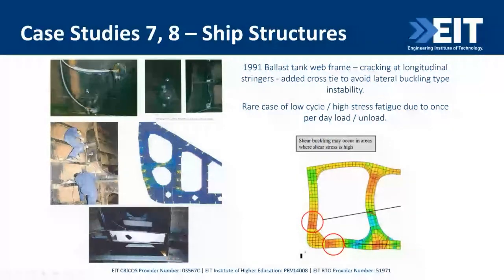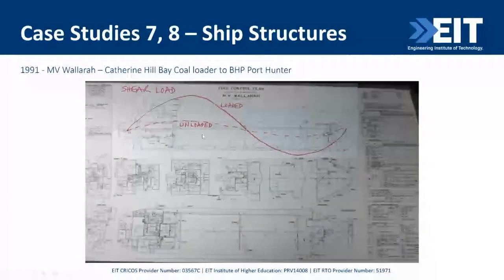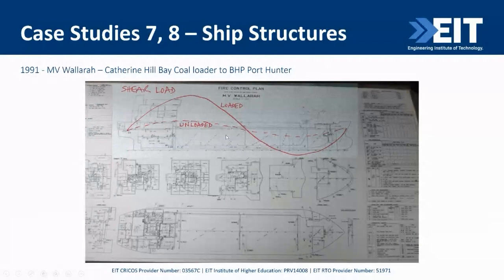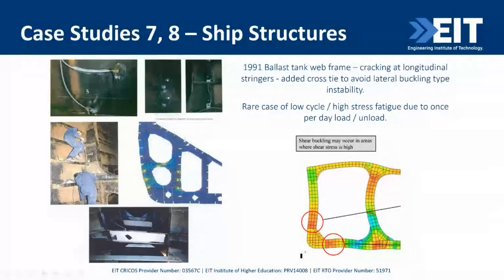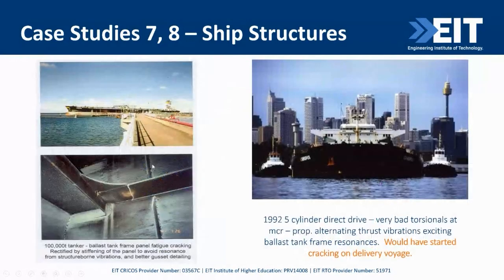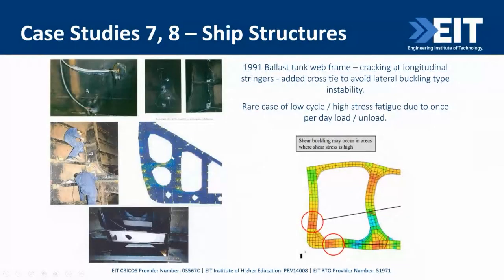and it was cracking at these lower longitudinal hull side stiffeners as well as further up on both sides. And the reason for that was the shear. Once per day shear loading, coal full and unload. This is the shear change through the beam of the vessel, and that shear was creating a shear buckling of the sides of the frame, which needed a cross tie, and that cross tie was added very well in Newcastle.